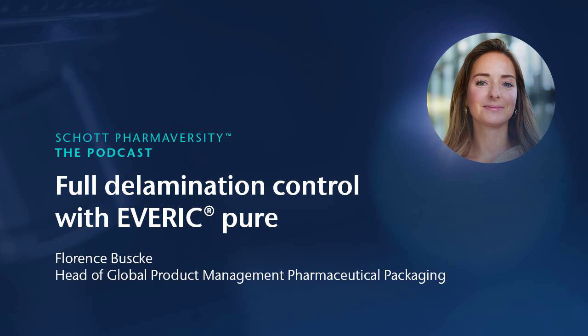So what differs now is that you can only do predictive studies for this phenomenon, as I said, with the leachables, to give results that allow for a graduated assessment of increasing risk of delamination, and also to detect early stages of this phenomenon so that you can select the appropriate container for your formulation and proactively prevent the delamination instead of just monitoring for the presence or absence of flakes. So if you monitor only flakes, you may not see seldom outliers that you may have with outlier containers.